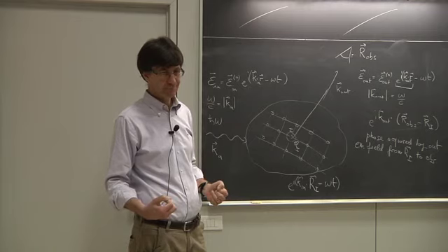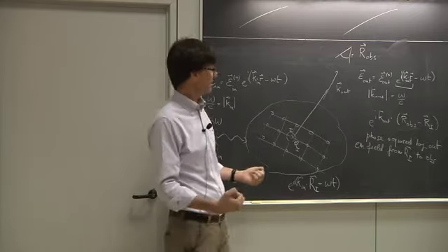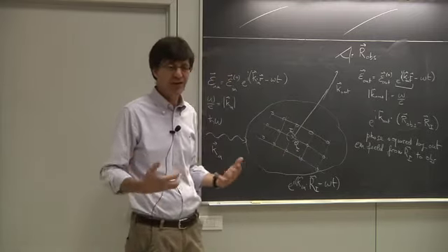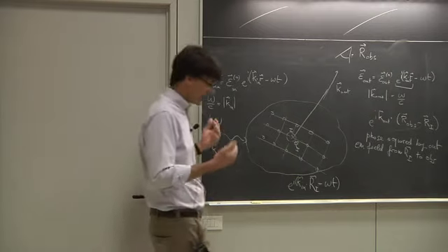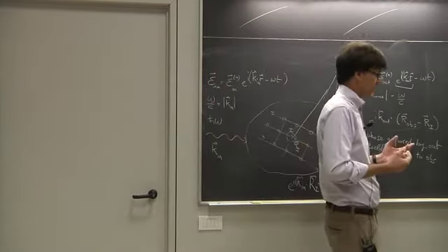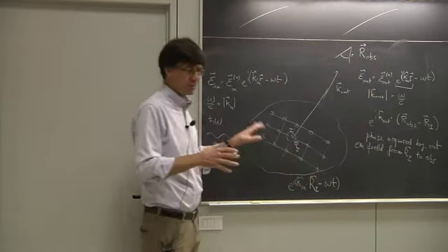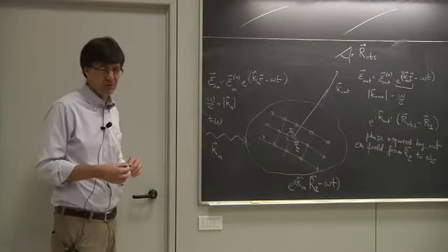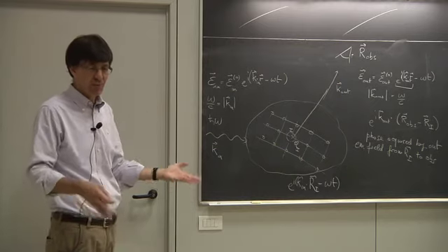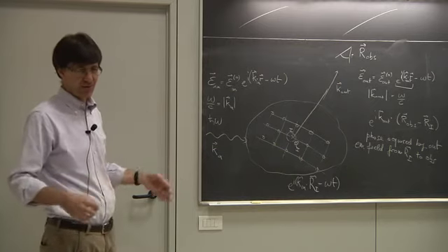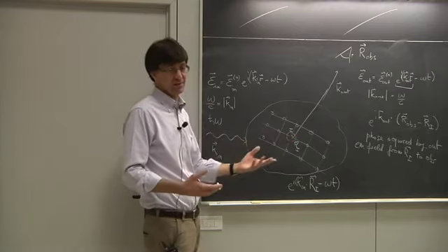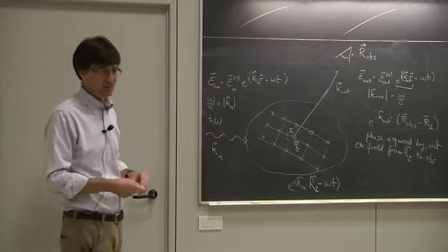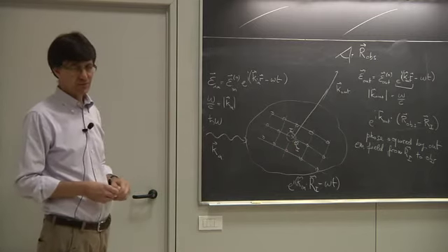Yeah, but they can emit radiation. Yes, but you won't be seeing any diffraction, because they will not carry information about the underlying lattice, right? So the extreme case of a free electron is a good one, because it's an example where you will not be able to extract the information about the nuclei, because the electrons don't even know about the existence of a regular lattice. So you need to somehow assume that there is some structure and there are atomic charges. Otherwise, you won't be able to extract any information from the system.